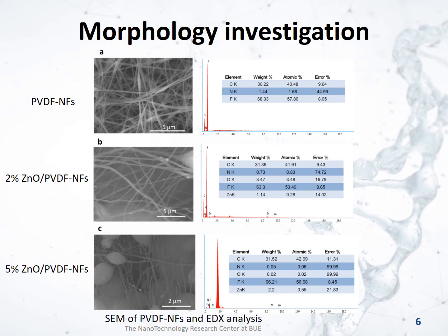After successful loading of zinc oxide on polyvinylidene fluoride and successful electrospinning of those materials, we investigated its morphology, which appeared by SEM to have the nanofiber structure. And we noticed that increasing the zinc oxide content led to an increase in the bead ratio in the nanofiber structure. Also, the EDX analysis indicated the content of zinc oxide in the nanofiber.